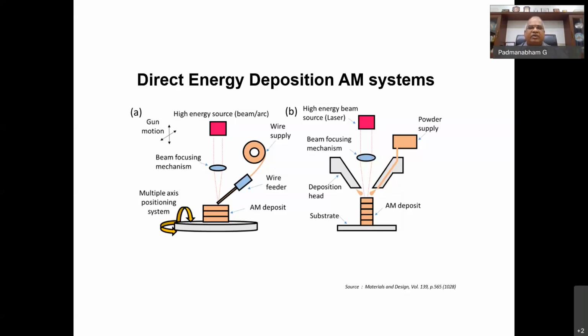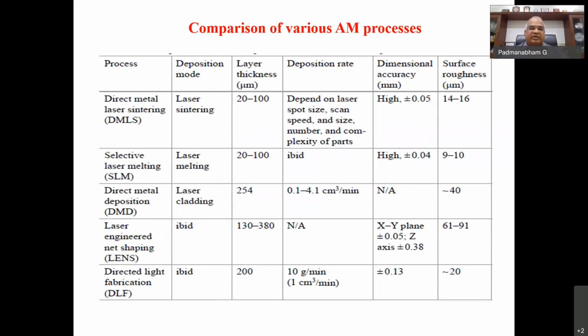Each of them have their own merits and demerits. We'll just briefly look at that also. For example, if we compare these two processes, like the selective laser melting method or the direct metal deposition method, the second and the third column. The first difference is the thickness of the layer that you can build is about 20 to 100 microns in this case, and 254 microns in the case of direct metal deposition.